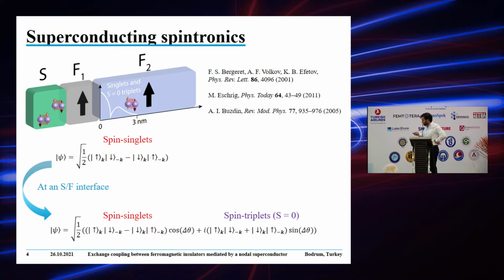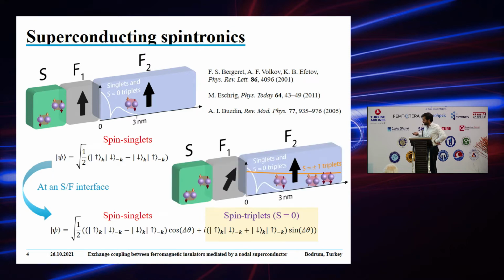But fortunately, for us working in this field, there were a few predictions at the beginning of this century suggesting that if you change one of the two ferromagnetic layers and introduce some magnetic inhomogeneity, then the spin zero triplet, which unlike the spin singlet is not rotationally invariant, can be projected along a different quantization axis, and you end up generating fully polarized spin triplets. Within the Cooper pairs of electrons, both spins are now aligned. These are fully polarized spin triplets, and in principle can be used for spintronics applications. This was the beginning of the field, and then there was a lot of experimental work based on Josephson junctions, spectroscopy experiments, and so on to prove the existence of these spin triplets.